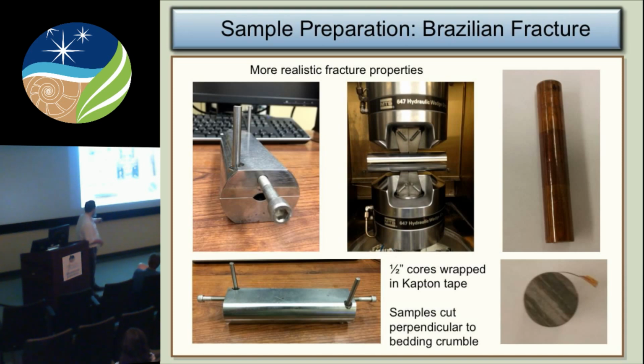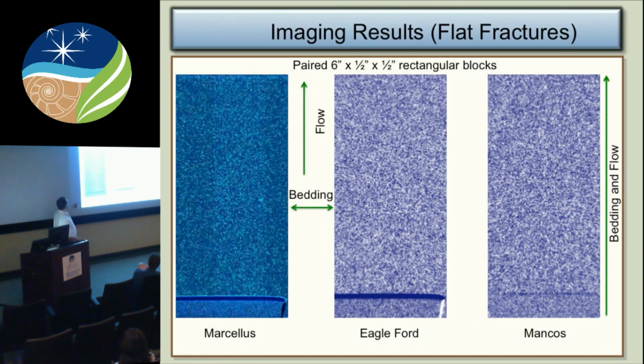On the other hand, we've also developed a system using an extrapolation of the Brazilian fracture technique where we can take a shale, or in fact I just did this with a granite on a larger scale, and make a real fracture within it. We'd put it in a press here and fracture it. And you can't quite see it, but there's actually a thin fracture that's broken through this sample. This is Mancos, this material here. We then wrap it. This is Kapton film, so that the outside is sealed, and then watch the capillary uptake.